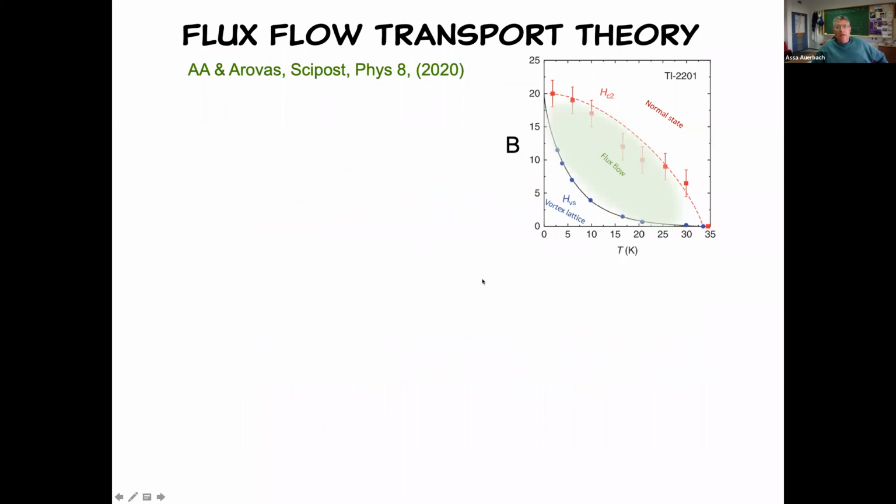So now we're into flux flow. Flux flow is a regime of superconductors in the temperature-magnetic field phase diagram, where if you look at low fields and low temperature, I described the vortex lattice. But if you increase temperature and increase magnetic field, and remember, these are thin films, you could have a regime where the vortices can move quite easily if you put any kind of force on them that would want to make them move. Once the vortices move, voltages will develop and the system will behave like a metal. But it's not a real metal, because the real metal is something you're going to see above TC at zero field, and that behaves according to the theory of metals we described before, or some other theory. It's quite different from this regime, because this regime is essentially a superconductor with a vortex lattice that is crawling along in some direction.